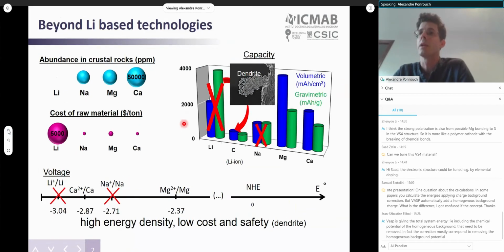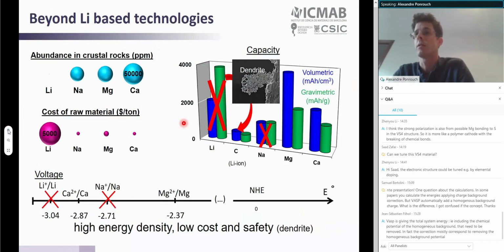And of course we do hope to be able to work safely with the metal anode, the same as for magnesium, which would allow us to bring significant improvement in terms of specific capacity on the anode side at least. With respect to the standard potential, calcium is actually 500 millivolts below magnesium, so we also have some good prospects for assembling very high energy density cells.